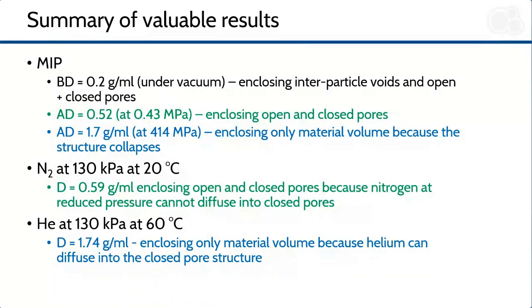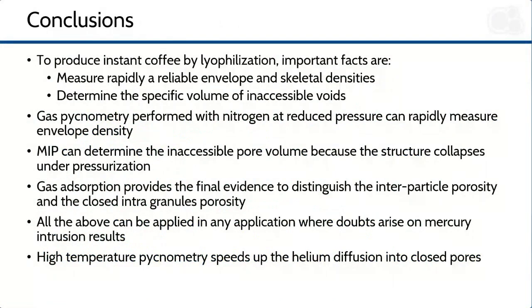in the inaccessible structure. For the case of producing instant coffee by lyophilization, it is useful to define a single, rapid and reliable technique to measure envelope and skeletal densities and to determine the specific volume of the inaccessible voids probably generated during the freezing stage. Gas pycnometry performed with nitrogen at reduced pressure can rapidly measure the envelope volume of granules, that is the volume including all closed pores but excluding the interparticle voids. Mercury porosimetry can determine the inaccessible voids volume because the structure collapses under pressurization. The BET surface area gives the final evidence to distinguish the interparticle porosity and the closed intragranules porosity.